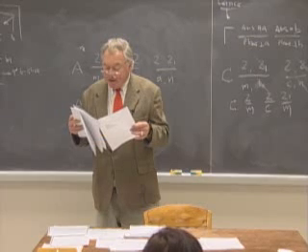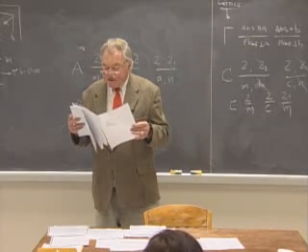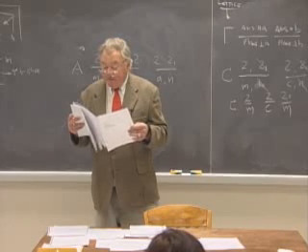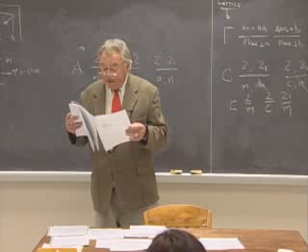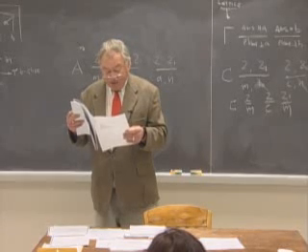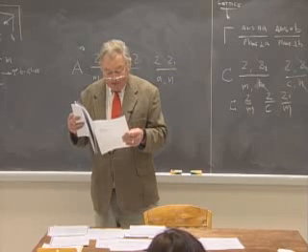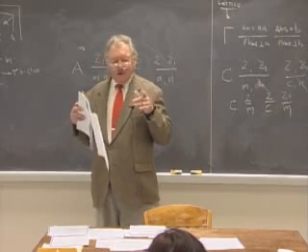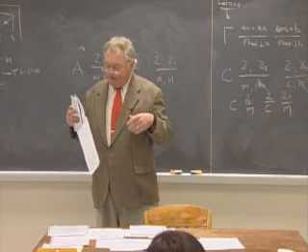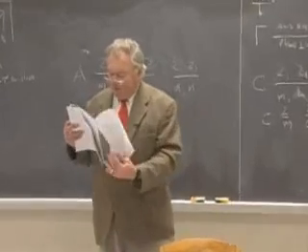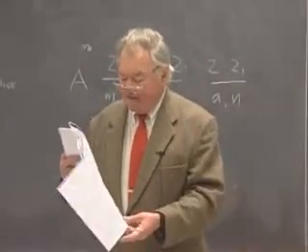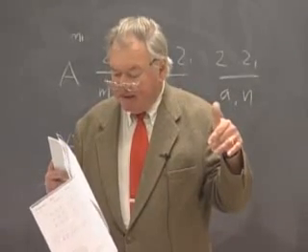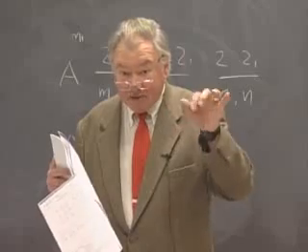And now if you look to the next page on the list of 16 atomic coordinates in the general position, you will see a number in parentheses in front of each one. The 15, for example, tells you that you get this atom from the atom at x, y, z by the operation of symmetry element 15, which turns out to be a mirror plane parallel to the x, minus x, z direction. And this is very, very useful if you want to describe a structure and you've labeled your atoms silicon 1 and silicon 2 if they're two different kinds of silicon ions in the structure. And then you're talking about a silicon-oxygen-silicon bond. And it's not at all clear which of the symmetry-related atoms are involved in that bond.